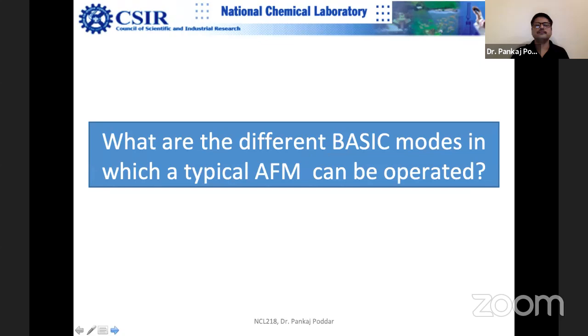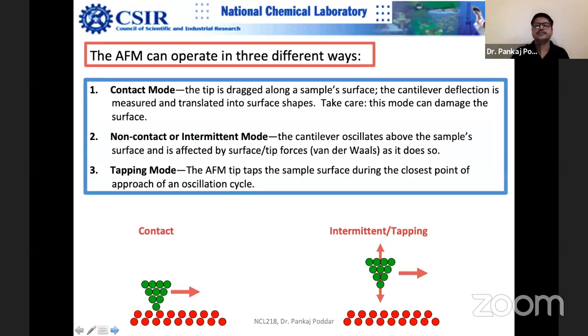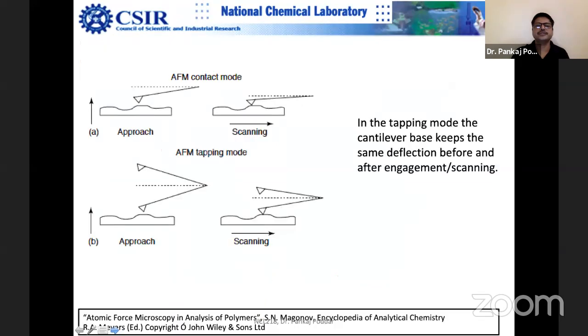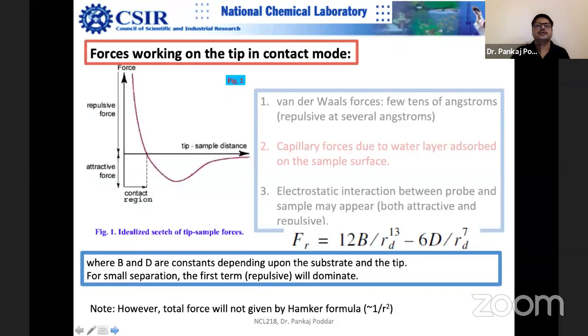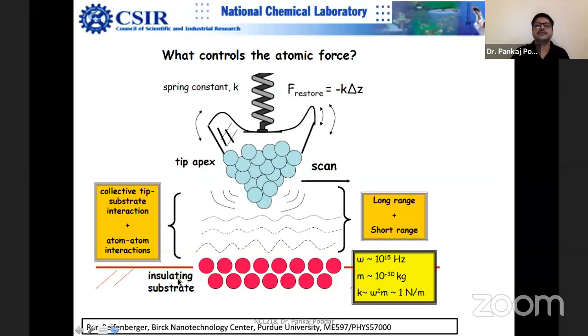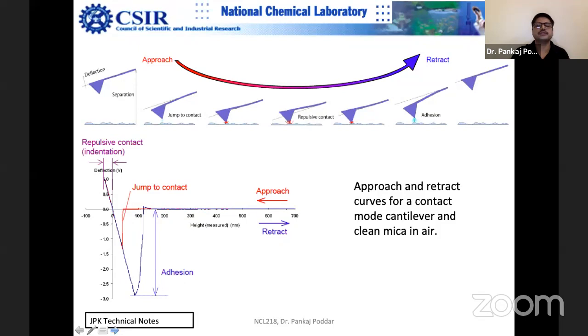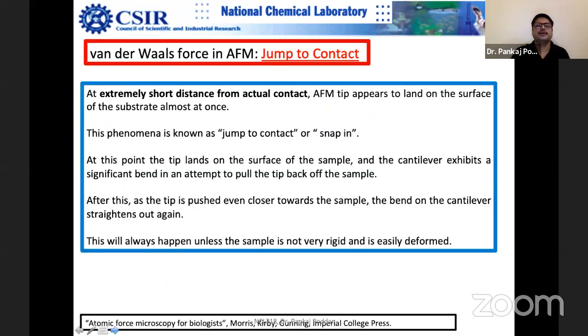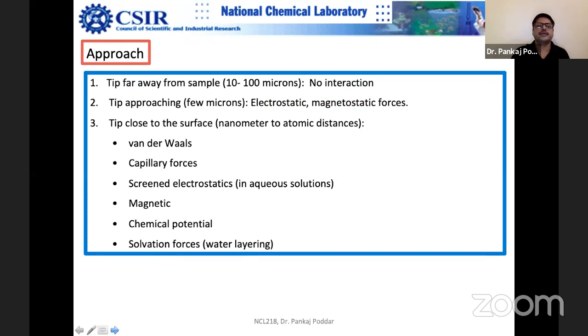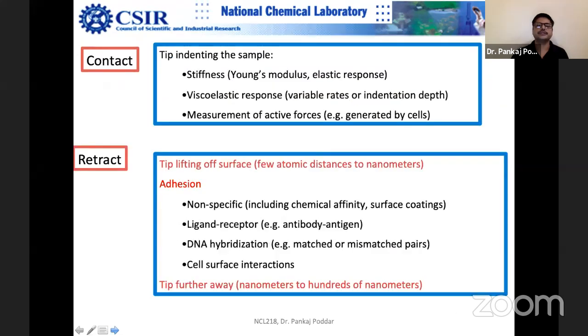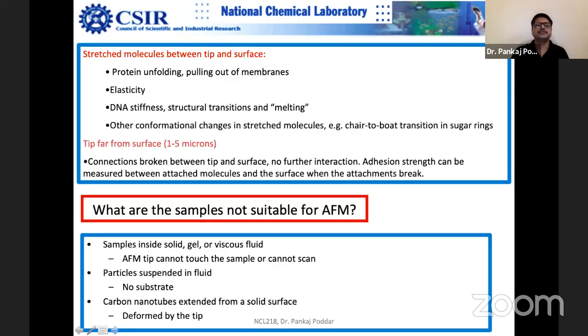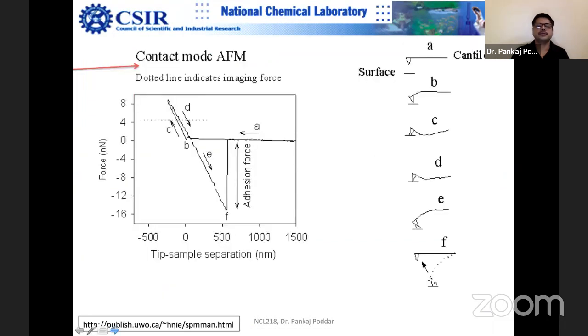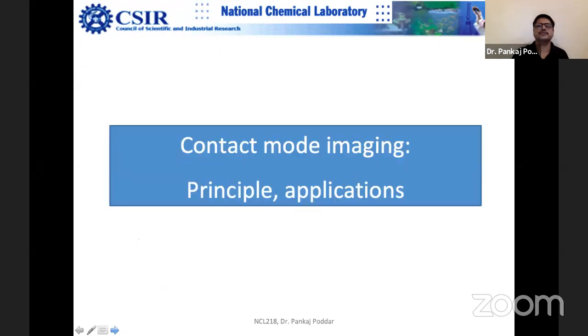And then I showed the difference between contact and intermittent mode, and we saw many animations. In the contact mode, I showed what kind of three information we get. This was the explanation for the force distance curve. If you are interested, that is also a very deep, separate lecture. So jump to contact and then jump off contact. I mentioned all those things, trace and retrace curves. These are very special things, especially for biologists; they are highly useful for people doing ligand receptor interactions and chemical force microscopy.